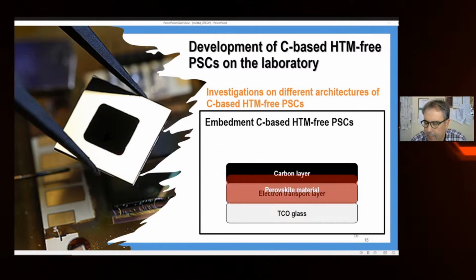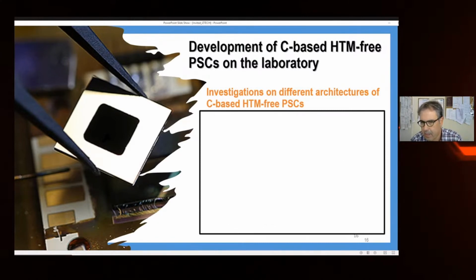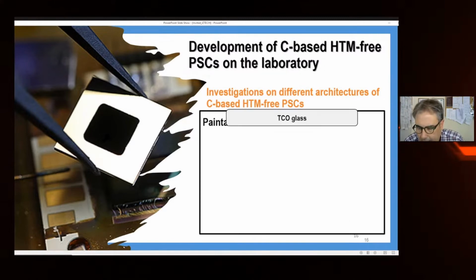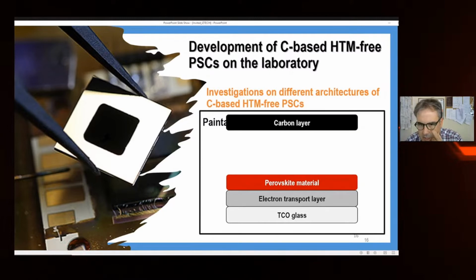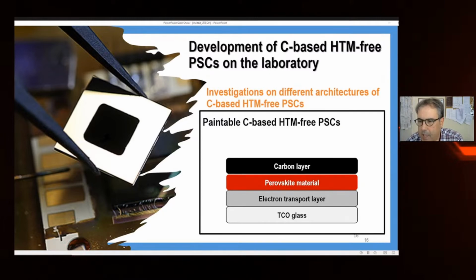Of course, we heat a little bit just to crystallize the perovskite, and this is the final device. But the most attractive structure here is finally the paintable carbon-based HTM-free perovskite solar cells. We have the separate layers of electron transport layer, which can be very thin, like titanium dioxide or zinc oxide. Then we put a layer of perovskite material. We'll see in the next slides how we can do it. And finally, on the top, we put the carbon layer.